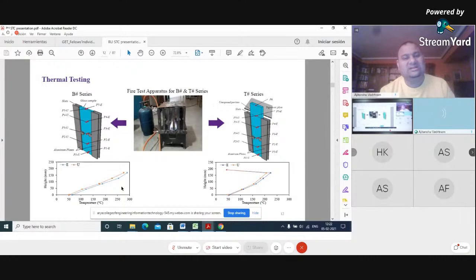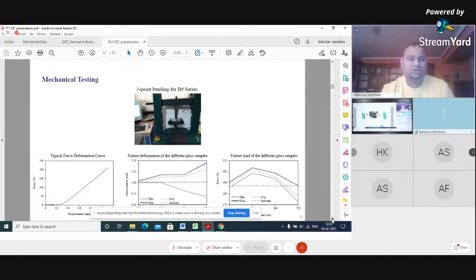But due to thermal gradient, any glass structure, any building material, specifically glass or laminated glass, does break because there is a gradient across the length of the glass. If there is a gradient of even 150 to 200 degrees centigrade, the glasses will start breaking. Even at a uniform temperature of 500 degrees centigrade, they will not break. So this is what we identified, and we worked accordingly on uniformity of the temperature on the glass. We incorporated certain treatments for that, and we were successful with our intent to an extent. We have done mechanical testing before fire and post fire, and in general the mechanical testing.